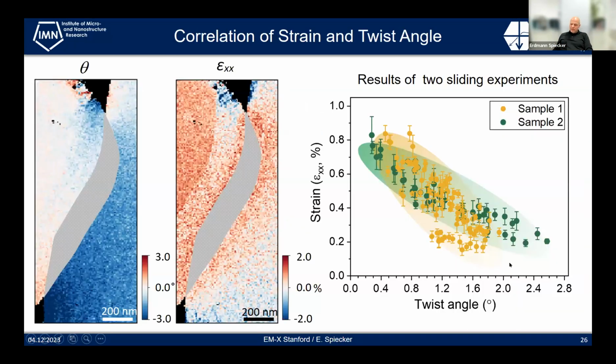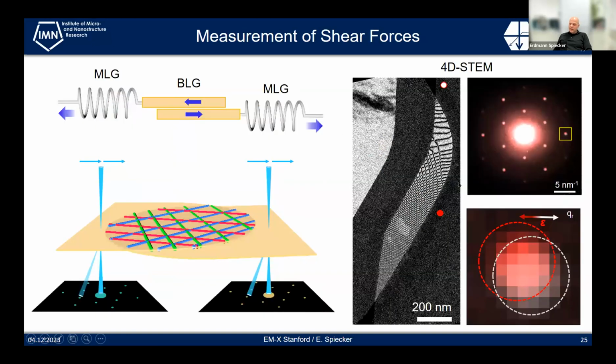how we achieve that. Oops, now I was too fast. It goes back. Okay, here on the right, you see we measure the diffraction pattern with 4D STEM at each position here, shown exemplarily for the red dot. And we compared it with a reference diffraction pattern, which is very close to an edge where there's no strain expected because of the free surface. And you see that there's not only a rotation involved, but there's also an epsilon, a strain, which indicates a straining along the strain direction.